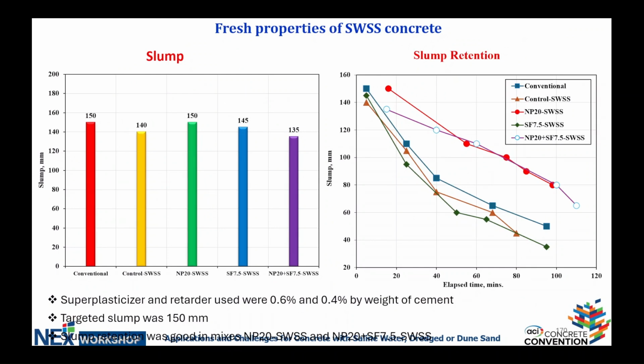So let's start looking at the fresh properties here. As you can see, the slides with the bars, there is really no difference between the benchmark and the other mixtures if we use the right admixtures to correct the slump in terms of a single measure of workability. The slump retention is another issue. This is really important to see what is the finishability of your material. And again, this can be corrected with the right use of admixtures. But you need to maintain good slump, meaning good workability, even after the critical item of the 1 hour and 30 minutes, as for example was indicated in the presentation about AC 574.